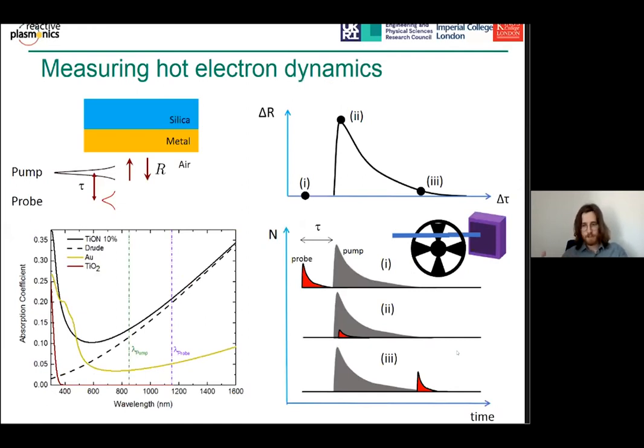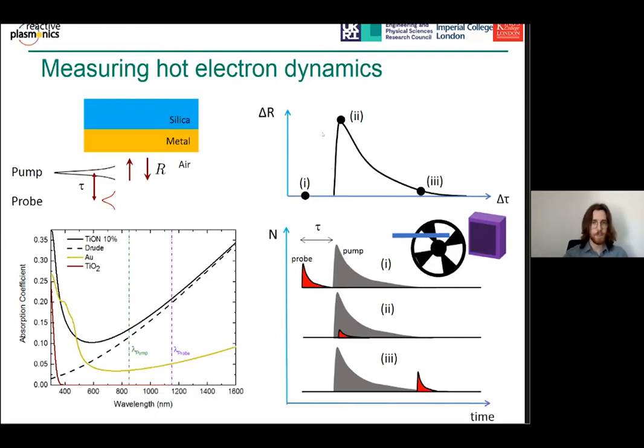So in understanding the deposition methods, depositing the material, operation wavelengths and their temperature stability, we also want to measure the hot electron dynamics. So if we're interested in using them in hot electron devices, we need to understand what's happening there. So with titanium nitride, again, we use pump probe spectroscopy to measure the hot carrier dynamics in the material here. So in pump probe spectroscopy, we excite with a pump, and then we probe with a time-delayed probe beam by chopping the laser. And that allows us to map out the excitation features here. So we can see the time delay and the lifetime of the hot carriers.